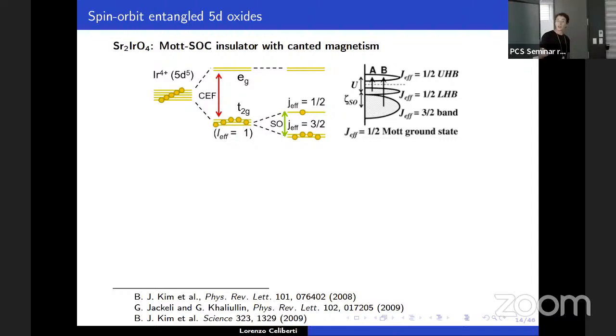But I'm sorry to interrupt you. You mentioned also the Hubbard model, which also opens a gap, so it becomes an insulator, right? But what you see here is that it would happen in these materials only at too large values of the interaction. Yeah, basically, if I remember correctly, you would need a U value of 1.2 electron volt... sorry, a large U, which for these 5D transition metals is very high. Usually the U is 1 electron volt. For the 3D transition metals, which are the materials with a larger U, you have something like 6, 7 eV. So for 5D, it's really large. Whereas when you add spin-orbit coupling, with a U of 1 eV you manage to open the gap.